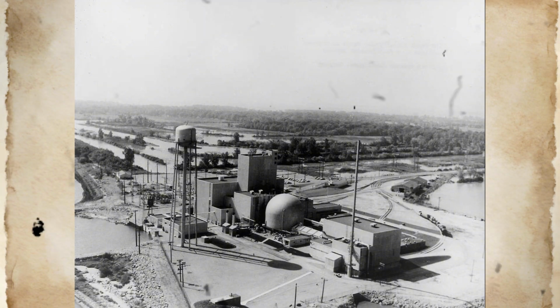Detailed metallurgical analysis of the recovered deflector plate and examination of fragments of its original mounting hardware revealed that failure had occurred due to fatigue cracking in the weld attachments that had secured the plate to reactor internal support structures. The fatigue mechanism was determined to have resulted from the combination of thermal cycling stresses imposed during reactor startup and shutdown operations and flow-induced vibration caused by sodium circulation around the plate during normal operation.